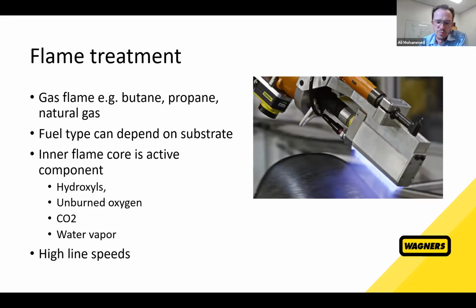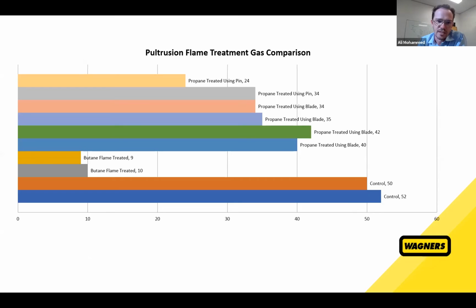One thing to note is that depending on what you're bonding to, the fuel type can change. We found more success with a butane type burner. So I've got a bit of a comparison here between a control set, propane, and a butane type flame treatment on our pultrusion. You can see the control surface hovers about 50 degrees contact angle. We apply propane flame to the surface. You can get it down to about 24 if you change the way that flame is applied. We use a blade type burner and a pin type burner. However, if you use butane, you get that surface contact angle down to a very low number. So for our pultrusion, we found most commonly butane gas to be the best if we're going to flame treat our surface.